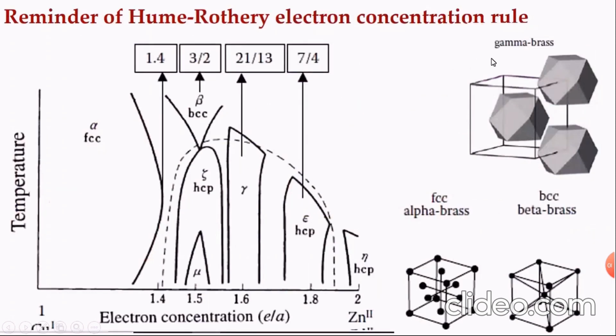Also, we have to take into consideration the electron concentration rule. Here, if we see the electron concentration with temperature for copper and zinc, we can see that in a certain range of electron concentration, we can have FCC. If we exceed it, for example 1.4, you can have BCC. If you exceed it further, you can have HCP with different types. So the type of crystal here is very dependent on the electron concentration.